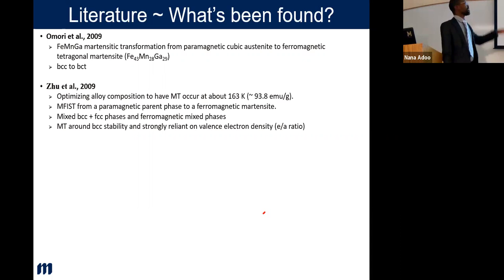Another researcher which I just saw was also Zhu et al. He actually found out the mixed phases, and he was just doing an experiment and realized that around a certain magnetic field, he could actually realize a high magnetization of up to 93.8 electromagnetic units per gram, which was one of the highest in the materials he worked with.